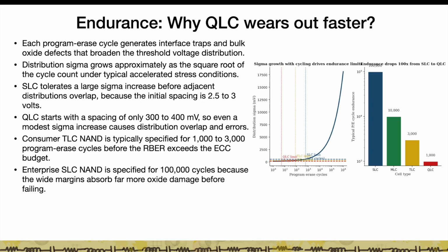SLC, with 2.5 volts of initial spacing and the same sigma growth rate, doesn't hit its limits until roughly 100,000 cycles. The same physical oxide, the same defect generation rate, 100 times more endurance, entirely because the initial margins absorb 100 times more damage before failing.